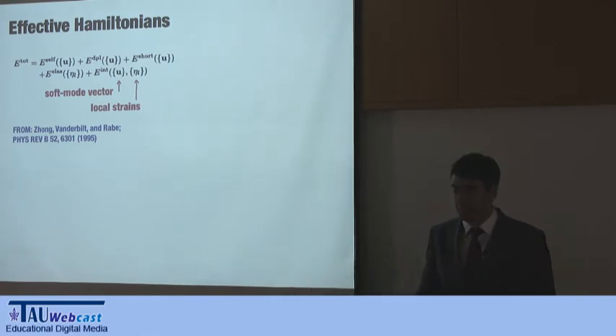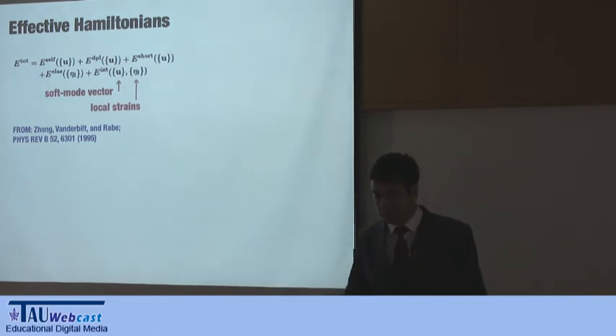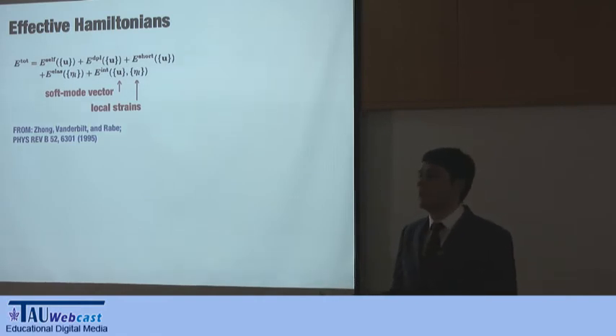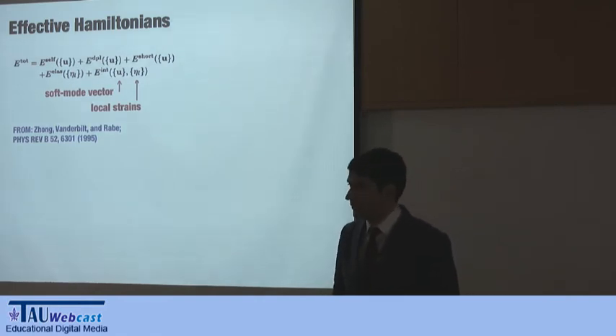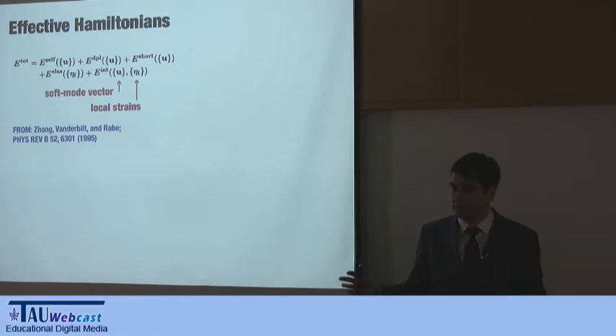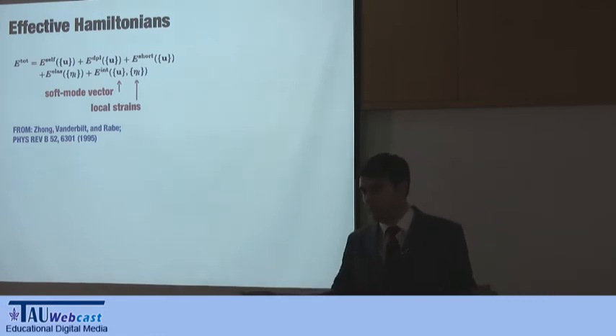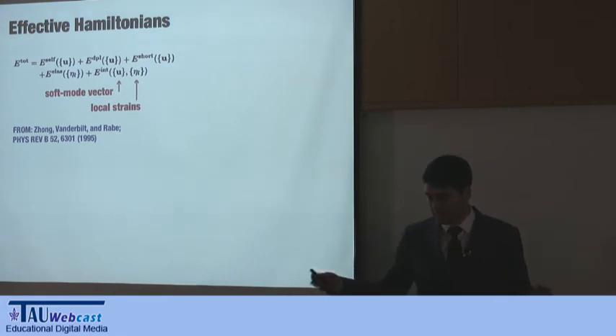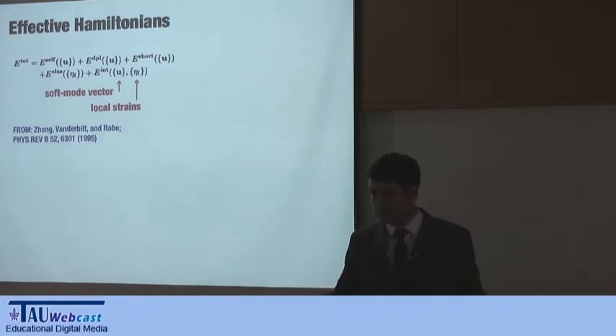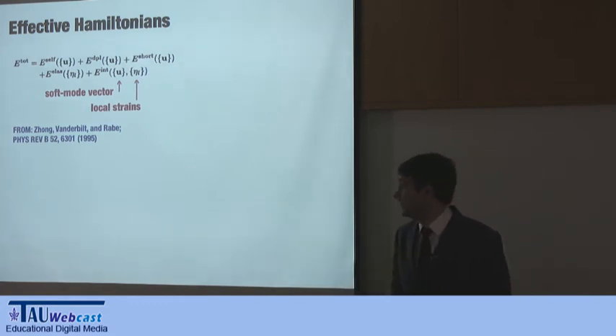something else. And to take into account temperature, in principle, you go to statistical mechanics and you have to do averages, weighted averages of energies of possible configurations. With DFT, this is going to be impossible because the system is too large. The fluctuations you can have can be on different length scales, so the system is large, and on top of it, you need to do many of these calculations. So there is no way to do it purely with DFT.